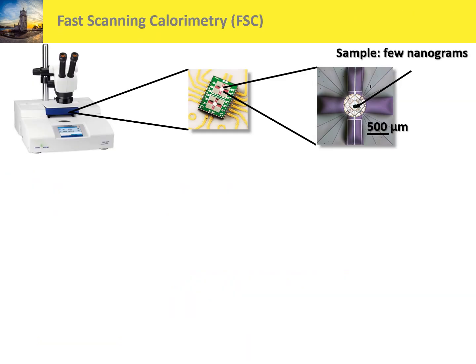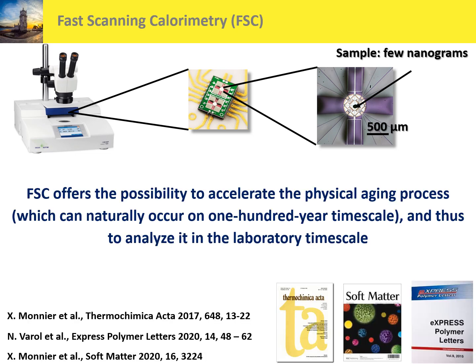So what about the fast scanning calorimetry? As shown here, the sample is placed directly in a sensor corresponding to the oven. The mass of the sample is around few nanograms, and we have shown that this technique offers the possibility to accelerate the physical aging process and thus to analyze this process in the laboratory timescale.